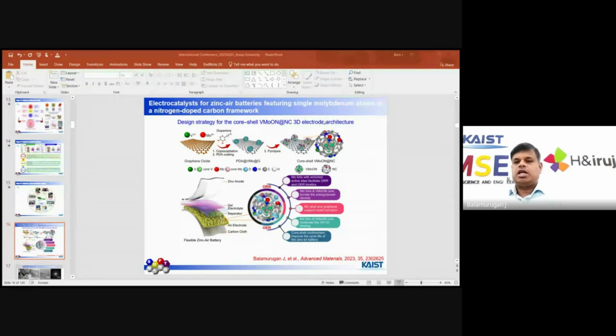This molybdenum single atom with the core, vanadium molybdenum nitride, is a new strategy, because we use the core-shell driven single atom. From the core-shell driven single atoms, different types of kinetics issues may be overcome, and we enhance the energy density and power density. The shell may prevent the active material from degradation, and the core-shell confinement may enhance the energy density, power density, and cycling stability of energy storage systems like a zinc-air battery.